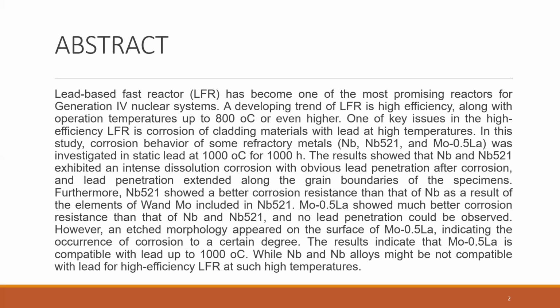niobium alloy. Molybdenum alloy showed much better corrosion resistance than niobium and niobium alloy, and no lead penetration could be observed. However, an etched morphology appeared on the surface of molybdenum alloy, indicating the occurrence of corrosion to a certain degree. The results indicate the molybdenum is compatible with lead up to 1000 degrees Celsius, while niobium alloys might not be compatible with lead for high efficiency LFR at such high temperatures.